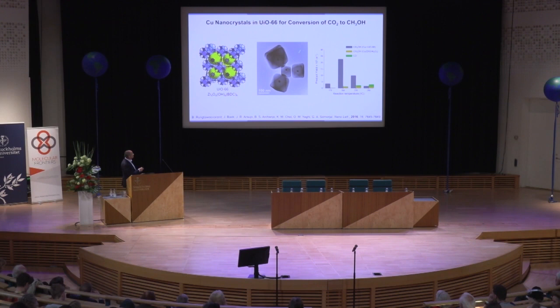We can also convert CO2 to a fuel — to methanol. Here's a copper nanoparticle trapped inside a nanocrystal of MOF. The MOF is a well-defined enclosure that allows CO2 to pass through the pores and be converted to methanol. The performance of this material far exceeds the state of the art. The conversion of CO2 to methanol is beginning to be solved. The idea of making a MOF that separates CO2 and converts it into a fuel is not very far from reality — we know that the components work. We need to put them together.